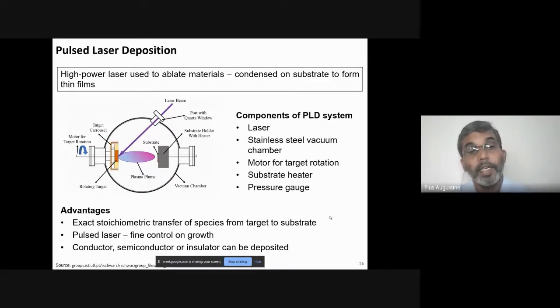And here the advantages inside, we can model it. Actually, it is quite a tedious process compared to many other thin film techniques because many parameters are involved. The distance between substrate and target, the pressure inside, then the energy of the laser, then the kind of gas available inside, what is the pressure of that gas, how much time we are depositing. Then after deposition, how much time we anneal. That is, during deposition, we heat the substrate, so that when the substrate is at a higher temperature, these incoming particles can move on the substrate and finally get deposited in a proper way, and exactly the same material will be transferred. So we will get a perfect thin film.